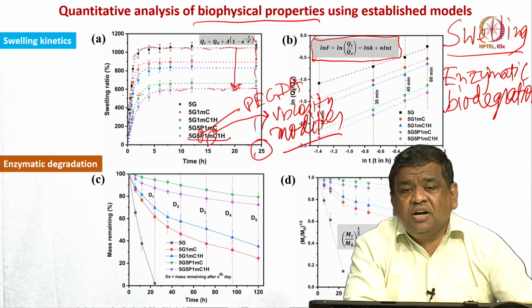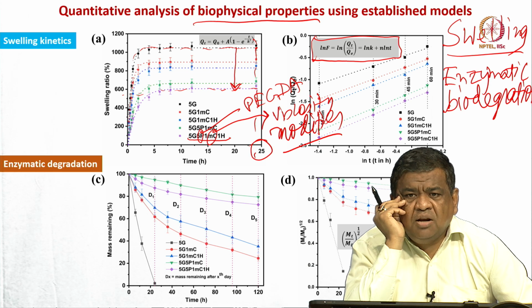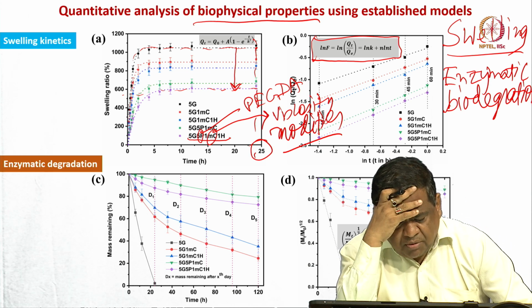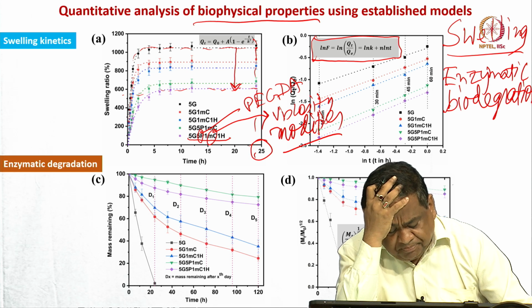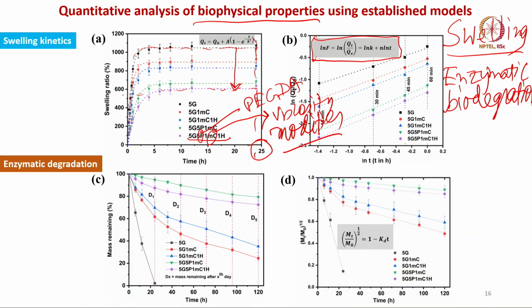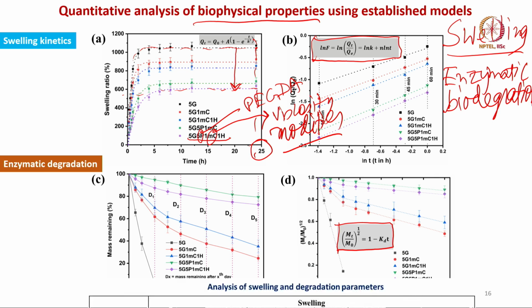But all these constituents were added in very small amounts in the 5% GelMA hydrogel, and this has a very positive impact. Now, enzymatic degradation was assessed essentially up to 5 days, like up to 120 hours, in collagenase solution, and the kinetics is analyzed by this specific equation: (Mt/M0)^(1/2) = 1 minus kd t. So, kd is the enzymatic degradation constant, and that has also been shown here, as to how the composition dependence in degradation kinetics can be evaluated.